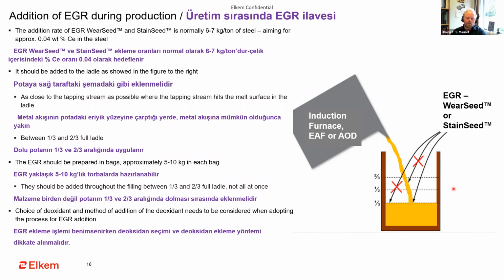So the way this addition is done is very important, and we immediately see it with regards to the recovery of the cerium. If this is not done in a proper way, then you get very little cerium into the steel. A lot of it is just slag on top of your steel, and it does no grain refining at all.